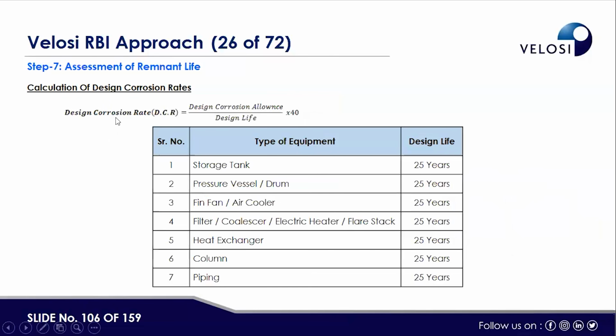In general, design corrosion rate is calculated from the design corrosion allowance and design life, multiplied by 40, in MPY. If it is the same, it could be millimeters per year as well. Normally, the design life of the equipment is like 25 years, but the actual life has to be assessed based on the available corrosion allowance and applicable damage rate.